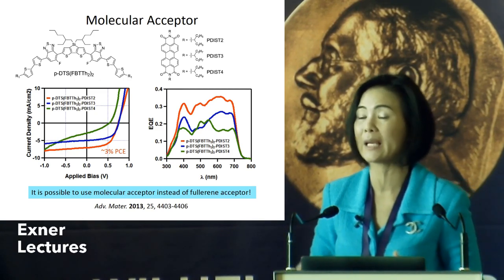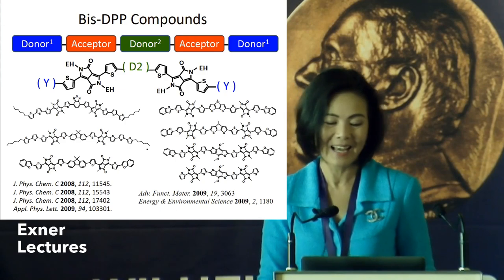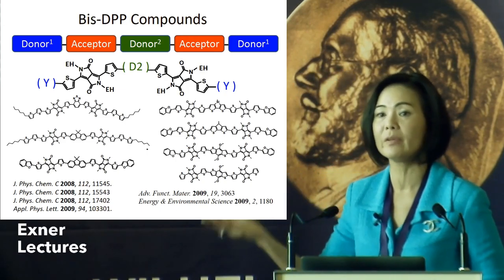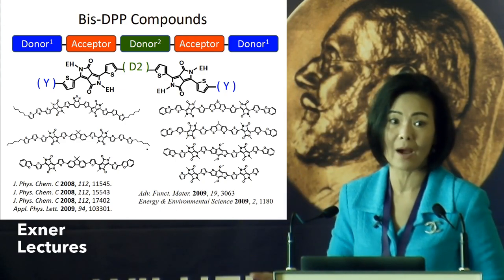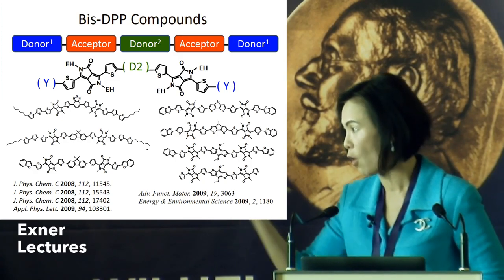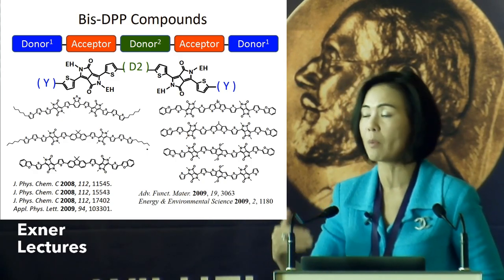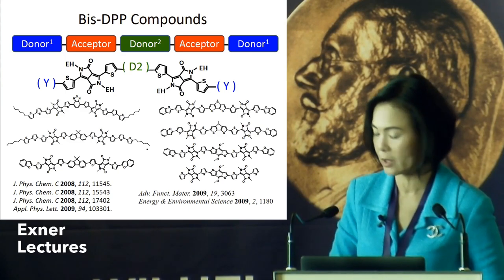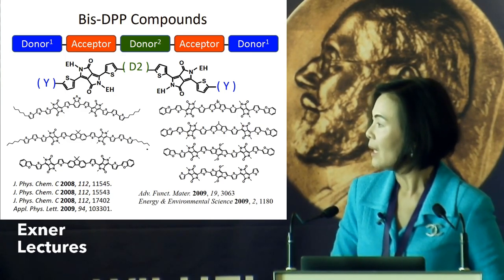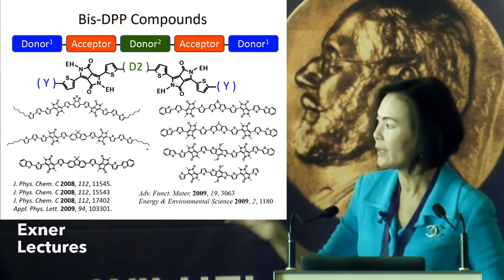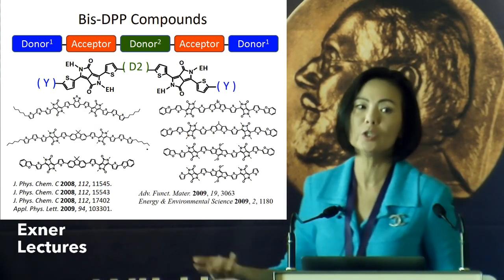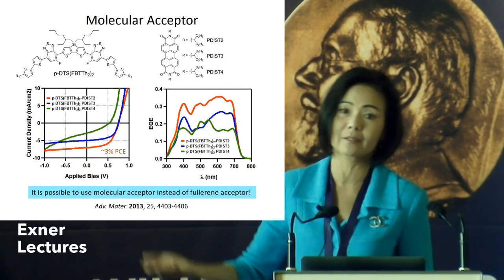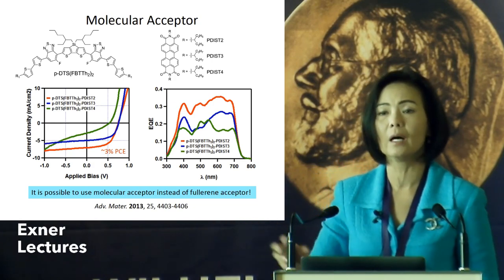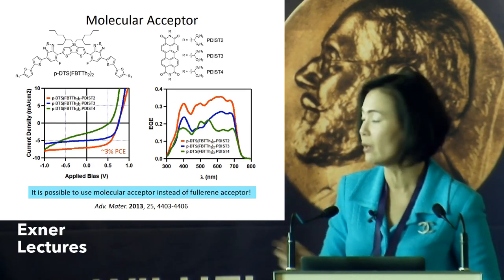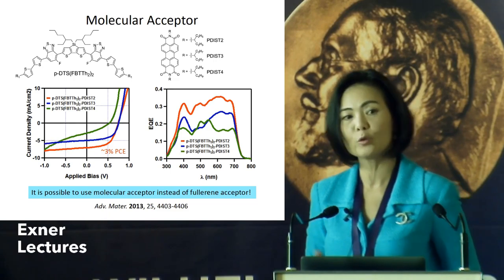At that point, people got very excited about that, right? Because at the time, the polythiophene solar cell could get about 5% efficiency, and with all the types of elaborate conjugated polymer donors, you could get around 7% efficiency or so. And so that got the field really excited. And then we turned to the molecular acceptor, because at the time everybody was using PCBM or fullerene derivatives. And so again, we wanted to give it a shot.